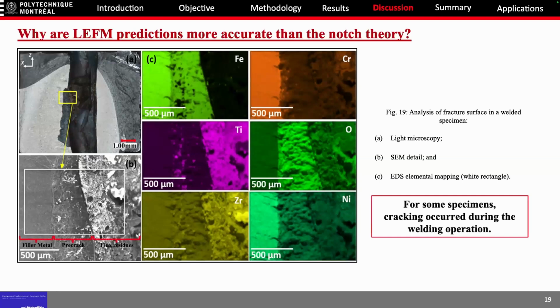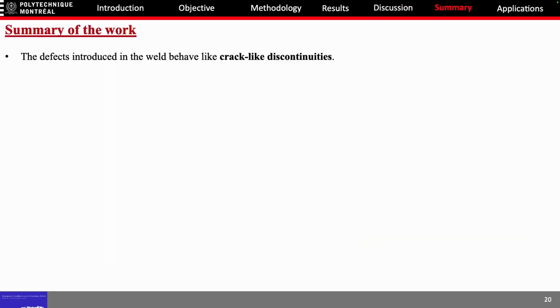Another reason why LEFM prediction is more accurate than the notch theory is cracks occurring during the welding operation. You can see the variation with the EDS elemental mapping, which shows titanium and zirconium, which represent the flux residues. There is a good distribution between the flux residues, the cracks, and the base metal, and some flux residues were present in the cracks. So it may embrittle the material.